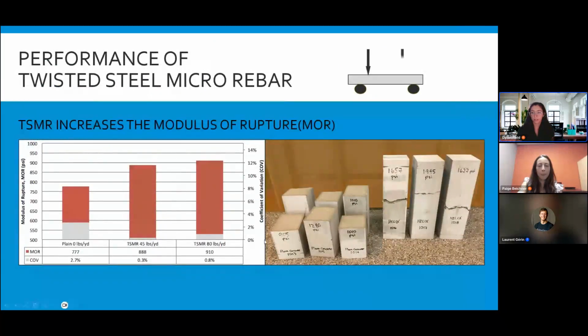So these are a few of the beam tests that we've used to determine the values listed in the report. And what you can see is as the dosage of the twisted steel micro rebar increases, so does the modulus of rupture of the concrete. So typically when you're doing a plain concrete design, you'll use about 5 times the square root of the compressive strength of the concrete. And when you're using a dosage of a twisted steel micro rebar or a steel fiber in this case, that can increase to anywhere between 9 and 12 times the square root of the compressive strength. So you do get a significant increase in capacity.